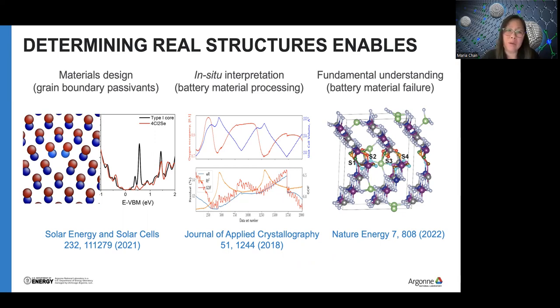But on the materials science level, you can do things like materials design. So with a realistic model of a grain boundary, you can put in different passivants on it and calculate the electronic structure changes. You can create 10,000 grain boundaries and put in the whole periodic table on it in 10 different positions. Or you can take the ones that are observed in experiment and do that. So I think that was a really nice method to do materials design that's realistic and relevant. That was published a couple of years ago.